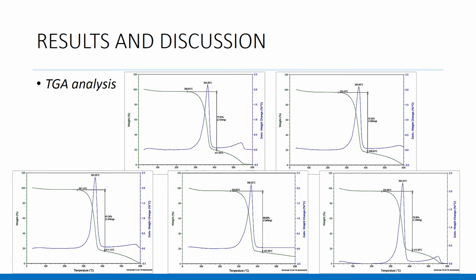The results from the TGA analysis show that all samples have 3 stages of weight loss. The less silver water was in the sample, the higher the weight loss detected. When comparing the weight losses of the treated samples examined, it was found that 2 milliliters of silver water increased the burn-up temperature of the paper by approximately 15 degrees Celsius.